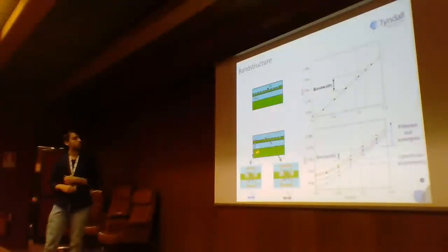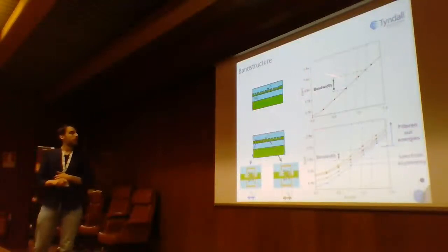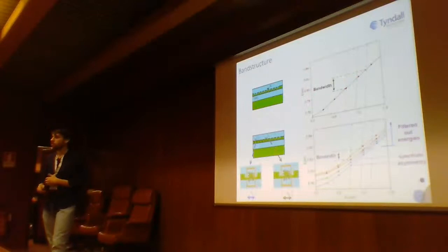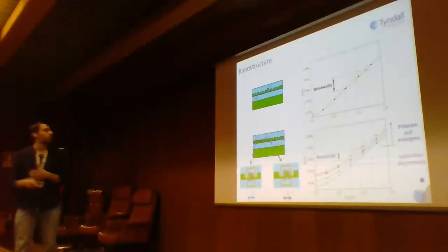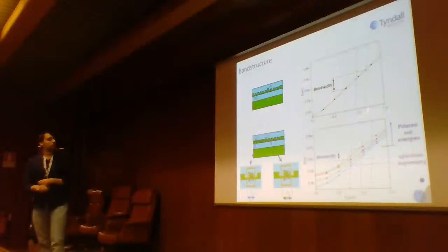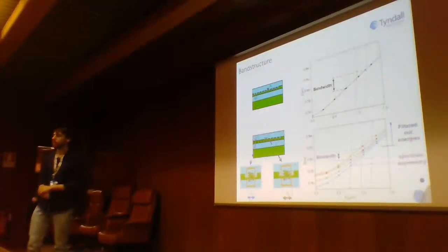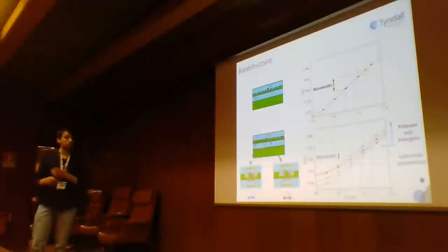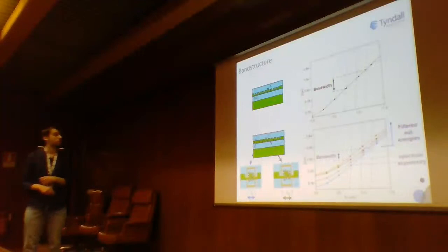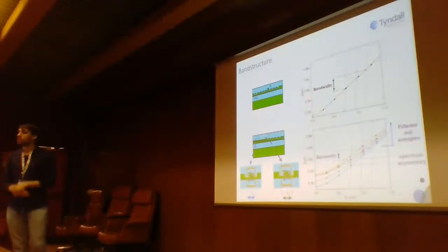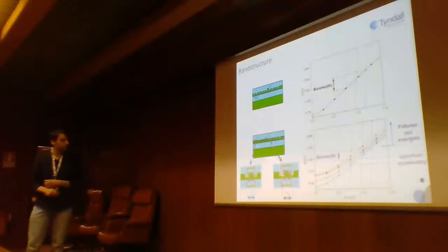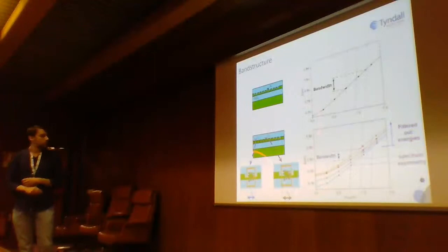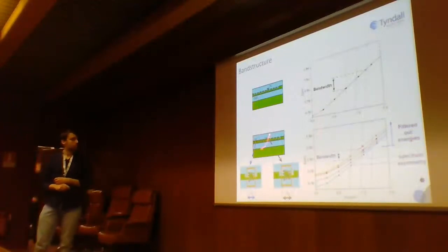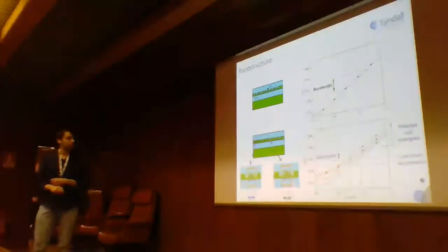So if we consider the uniform structure again, and we are taking the band structure in the region of 0.8 electron volts, that means our 1550 nanometers, that is the wavelength that we use to tune this structure, we get the overlap between the band structure and the Fourier transform of our Gaussian source. So again, the fiber that we're using to shine on the top surface of this object, then we are able to get again the bandwidth of our grating coupler. Instead, if we are considering a non-uniform grating coupler, in this case the only thing that we can do is to consider each period of the grating, reconstruct the uniform grating coupler associated with the different periods of the grating, and get the bandwidth of this non-uniform grating coupler.